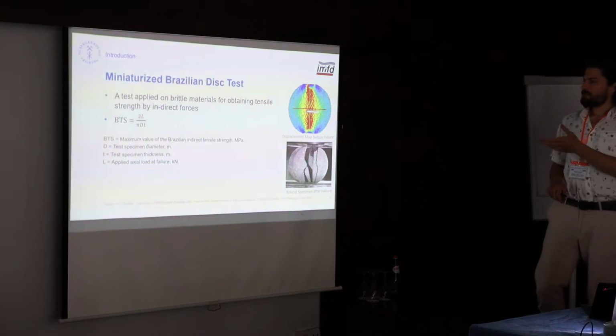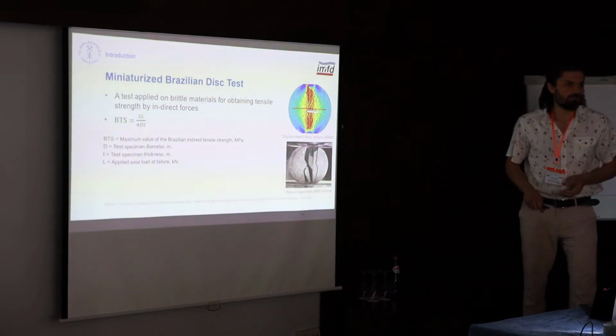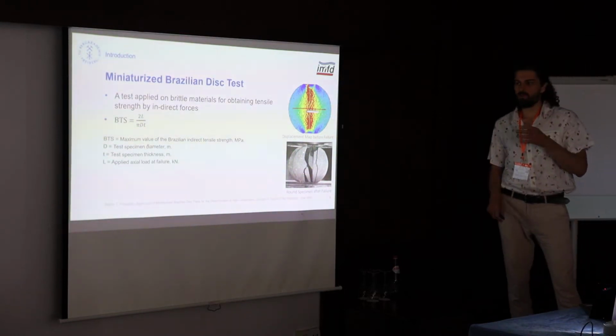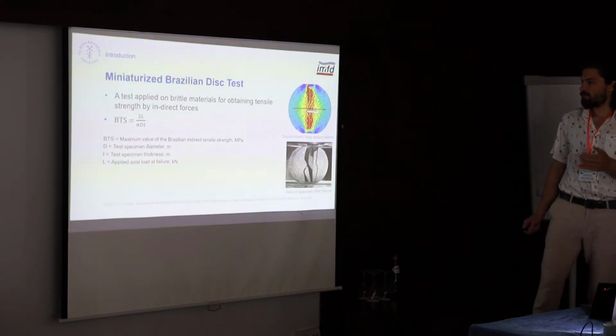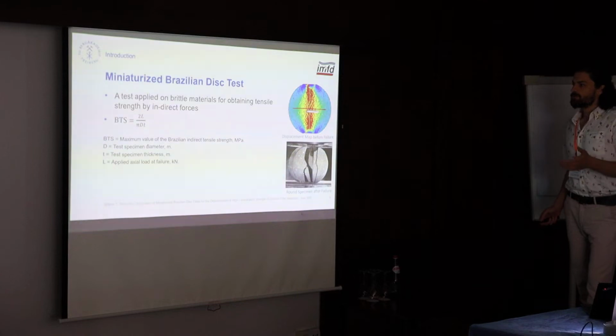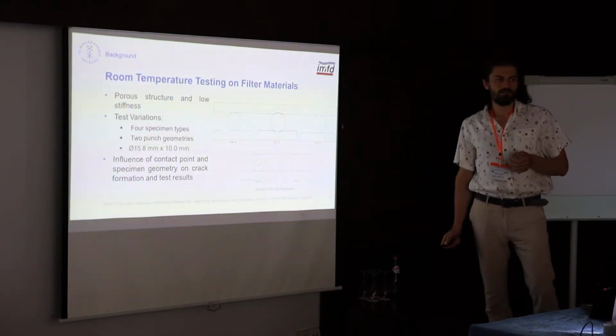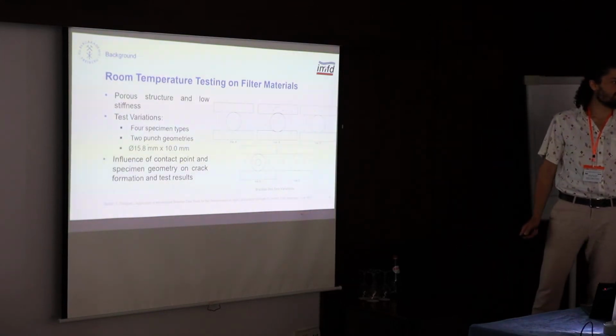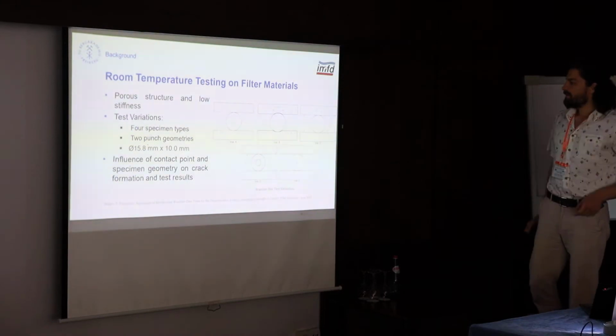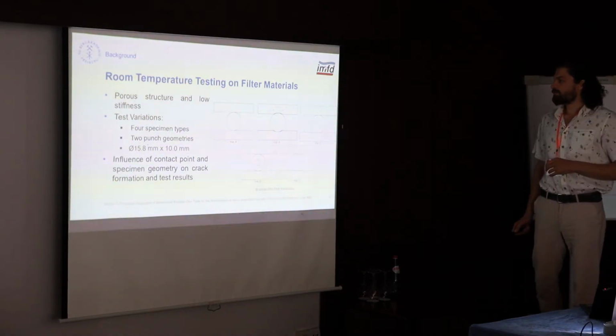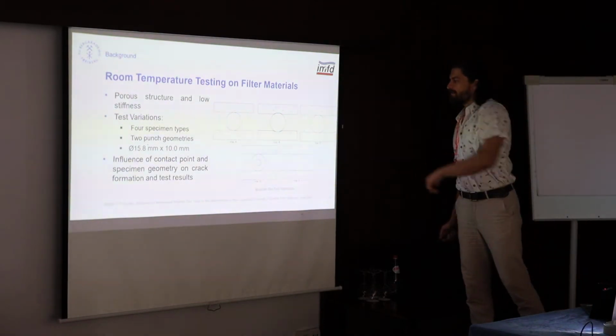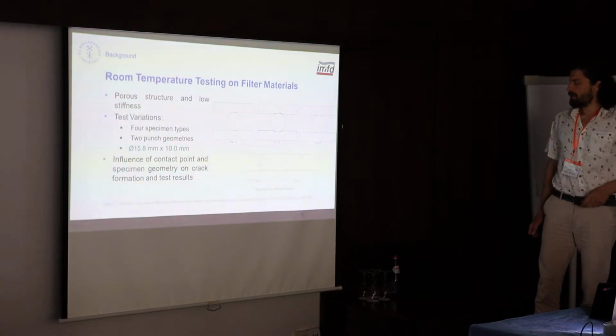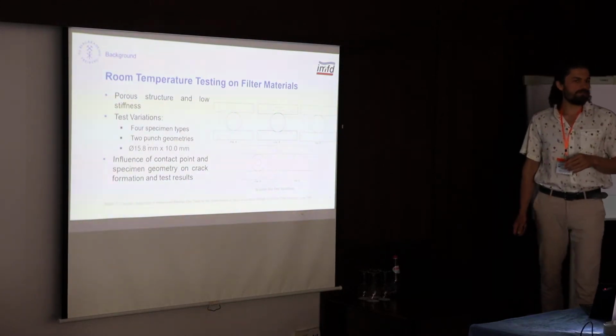As it seems easy to interpret for stiff materials like granite or concrete, in case of filter materials, due to their pore structure, it's not the case. So there are more complications to that. Therefore, at first I wanted to study the different test variations, by adjusting the specimen geometry or the punch geometry. So you can see here 5 different variations with flat punches and curved punches applied on the round specimen, and then a flattened specimen on the contact point compressed by a flat punch, and 2 other specimens with different aperture ratios of the hole to diameter ratio compressed with flat punches.